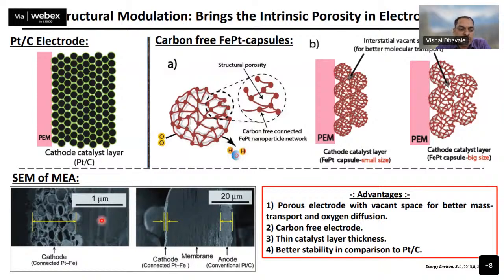Looking into this SEM, you can see the conventional PtC with the same Pt loading of 0.3 mg. You can see the thickness is around 10 micrometers. With the same Pt loading at the cathode side, this is the capsule structure, the cross section of it. You can see the difference in the thickness of the catalyst layer. So we can avoid many other problems in the fuel cell, like mass transport problems, and the diffusion resistance problems can also be taken care of with such a nanoframe structure. These are also carbon-free systems, so we can avoid carbon corrosion in the system.